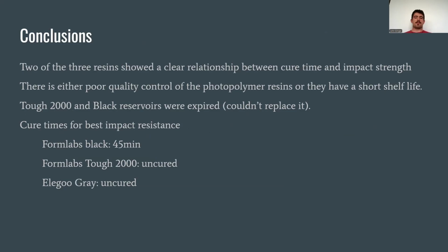The results of this experiment were that two of the resins display a clear relationship between cure time and their impact strength, the Tough 2000 and the Elegoo. Due to the Formlabs resins being expired, it is also thought this played a significant role in the recorded values, being significantly lower than the published values from Formlabs. Unfortunately, since there is no data available for Elegoo resin, they could not be compared to anything known. The tanks used for the Formlab resins were also expired due to no other option being available, which may have also led to the deviance from Formlabs' value.